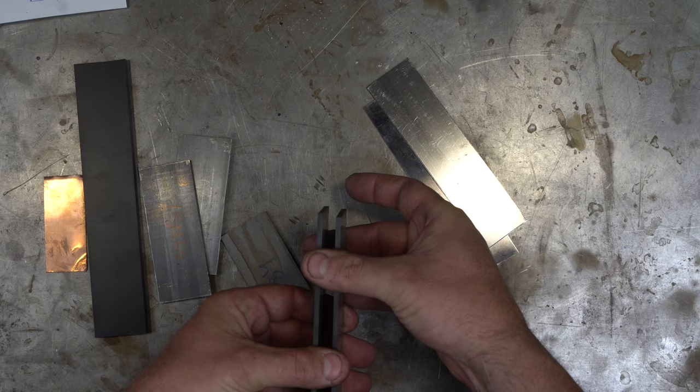Remember a note about kumai. So when you're doing copper, remember you're not forge welding and it's okay. If you're doing a regular sanmai, it's all steel. I'm going to be forge welding steel. If I don't have thick enough core, I can just take two pieces together. And then say that's my core and then do the cladding on either side. That's fine because my core is going to get forge welded together. If you're doing a kumai, you cannot forge weld any steel. You cannot have multiple layers of steel together. You can't do this because you're never going to get the billet hot enough to forge weld this without melting out the copper. So either get thicker stock or forge weld this first and then put it in so that you have your copper here and then your cladding and whatever you're going to do. So remember no steel back to back inside of a kumai.